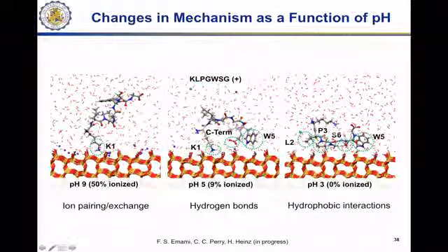If we have a lower pH with less ionization, then suddenly other residues join. At low pH, it's almost like a hydrophobic depletion interaction that was also observed in an experiment, which leads to the binding of several residues, even though it's weaker than the ionic interactions.